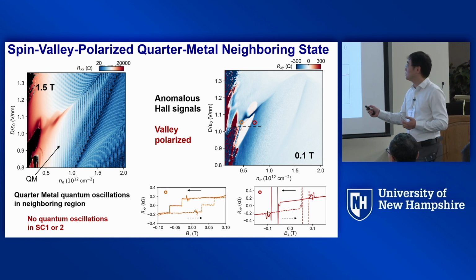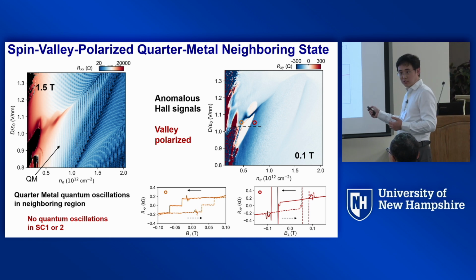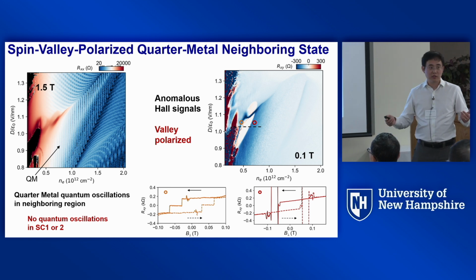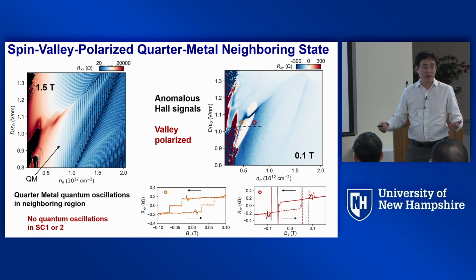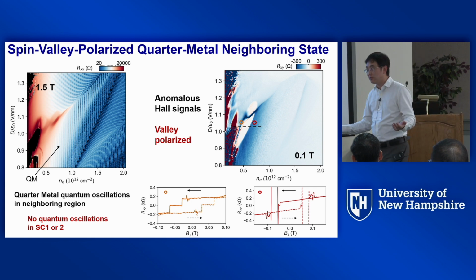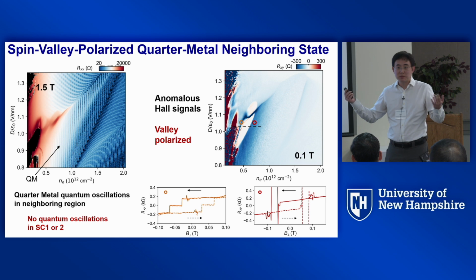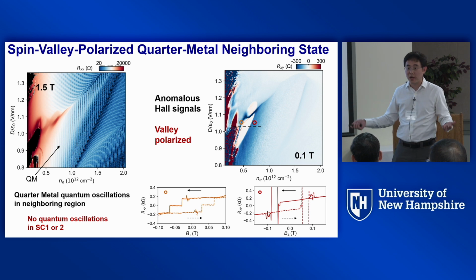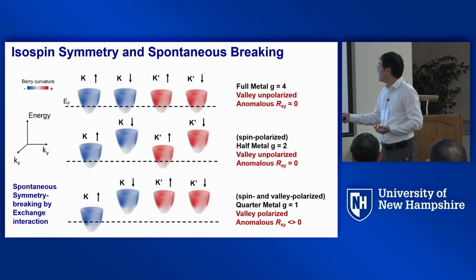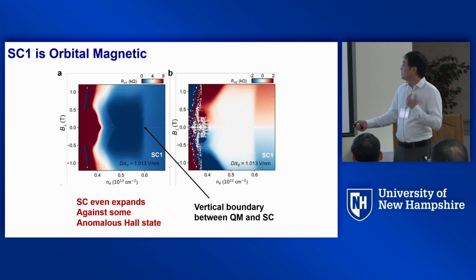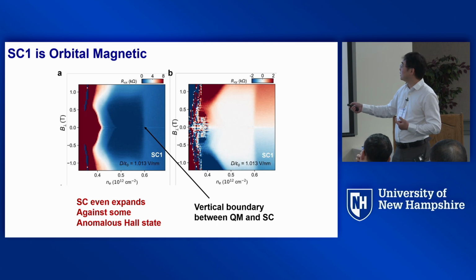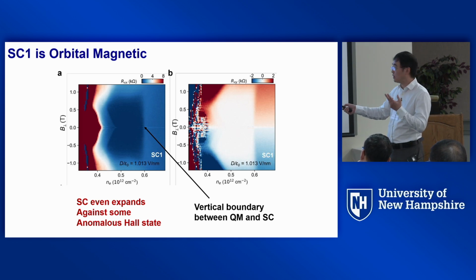And the superconductivity is right next to it, okay? So you may wonder, is the superconductivity also stemming from a spin and valley polarized pocket? That feels really weird because that gives you big momentum of a Cooper pair. And also means the spin is polarized, so it has to be a P wave, at least. Okay? Let me show you what we have now. So this is cutting through SC1 as a function of density, okay? To the right-hand side is that quarter metal, spin valley polarized.